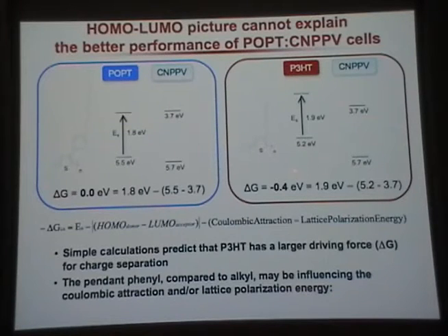So the P3HT has a larger driving force. If I just look at the HOMO-LUMO diagrams to split the exciton with the POPT, the P3HT has a higher absorption, a higher extinction coefficient, and yet the current is larger in the POPT cell.